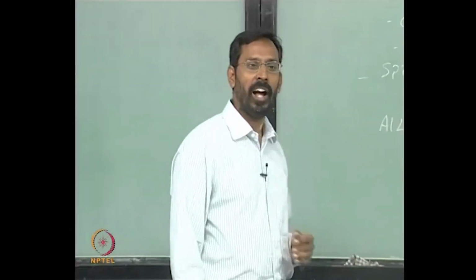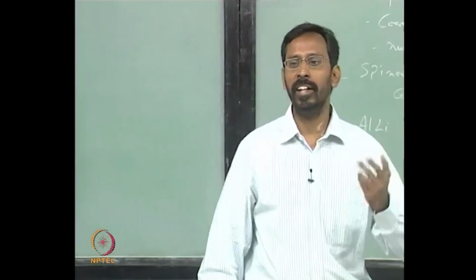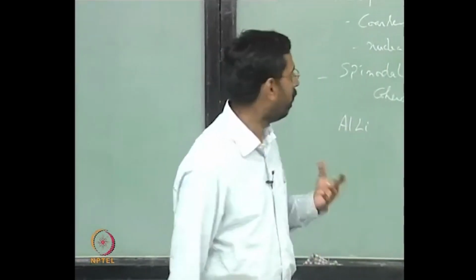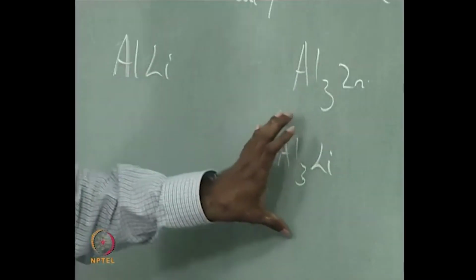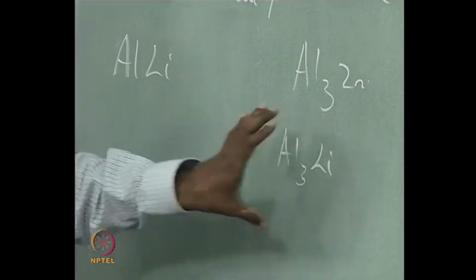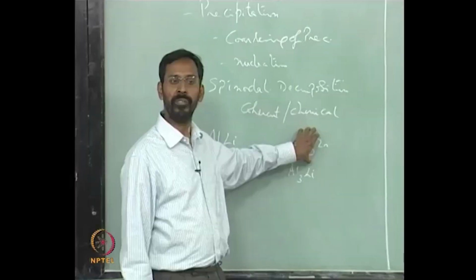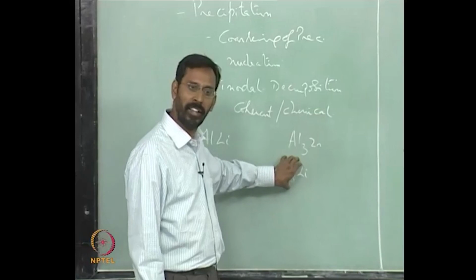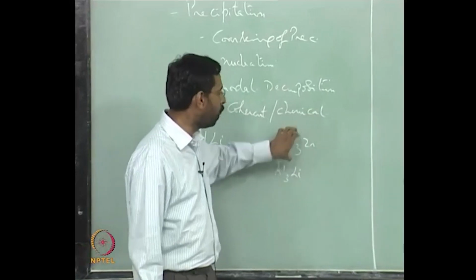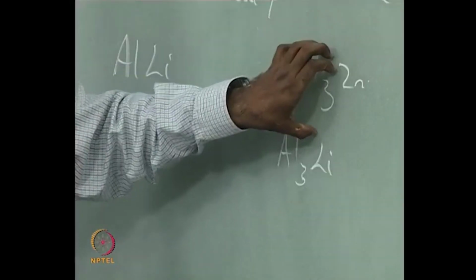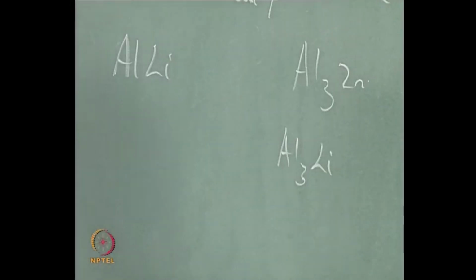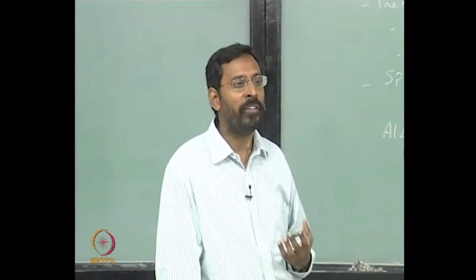So here aluminum will occupy the face centers, lithium will occupy the body corners, and that is how you get an ordered structure. And what they say is, because this is also cubic, it can easily nucleate this, and once this nucleates on that, inside the Al3Li you have an Al3Zr. So every Al3Li particle will have almost like one Al3Zr particle inside.